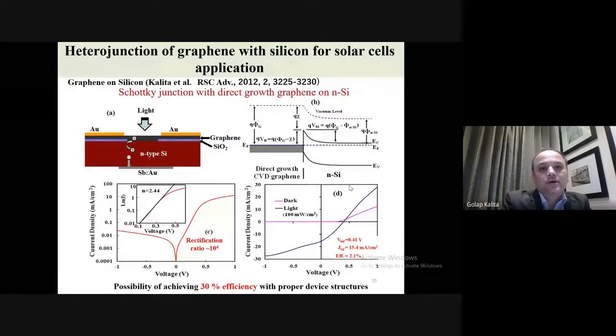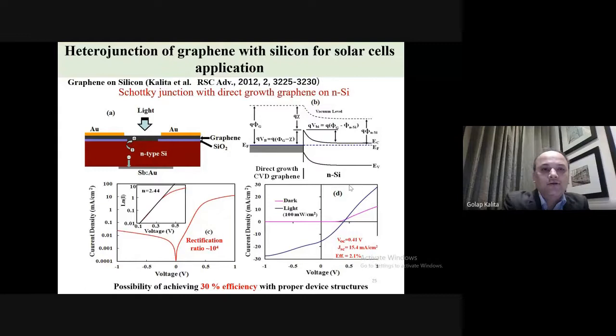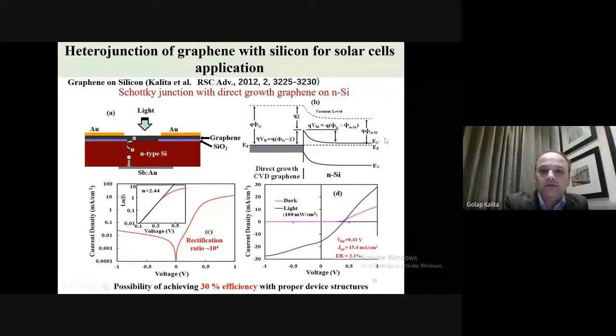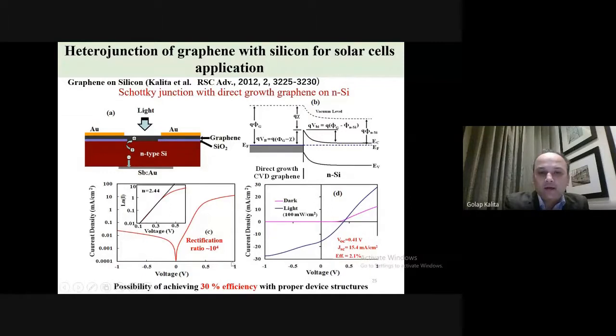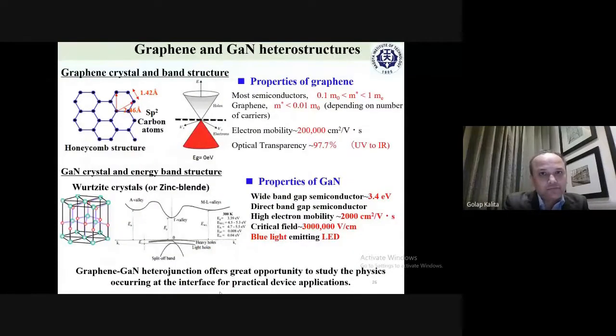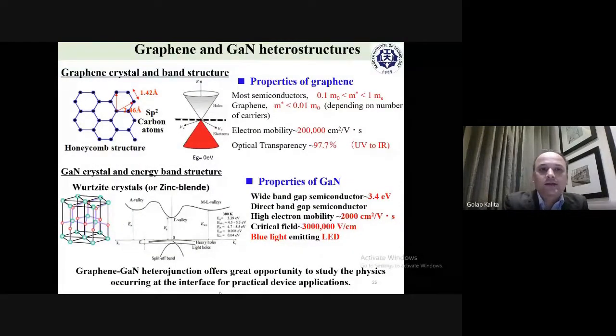We can make photovoltaic devices. If we deposit graphene on n-type silicon and make a photovoltaic device, it forms a Schottky junction, and with this type of Schottky junction you can now achieve maybe 2 to 5% efficiency. There are some papers whose theoretical analysis shows that you can achieve around 30% efficiency in this type of solar cell. Then we integrate graphene with gallium nitride.